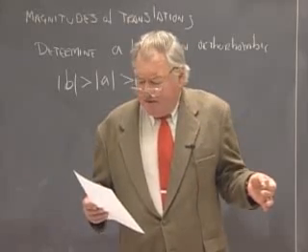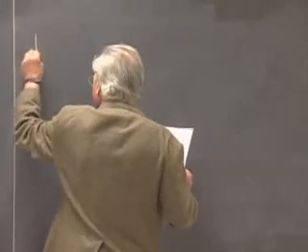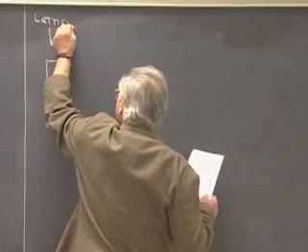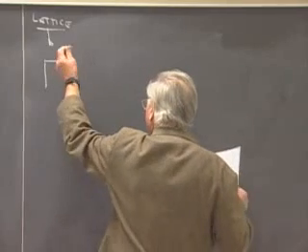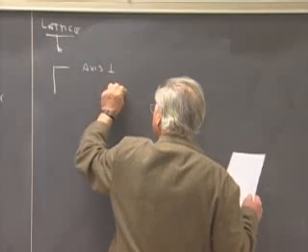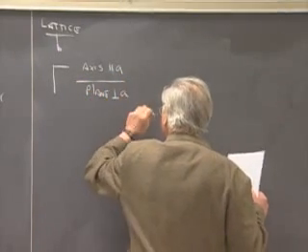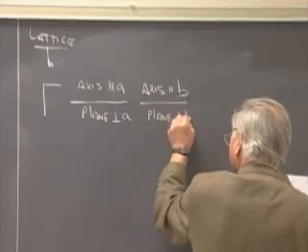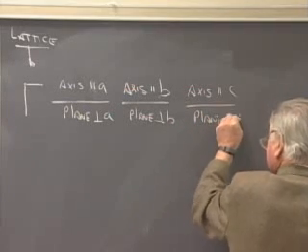All right, what symmetry goes first? And here, again, for orthorhombic, we need a convention. And the space group symbol has a symbol for the lattice type. And we've seen that the capital C that comes first indicates that there is a C-centered lattice. And then what one does for orthorhombic is give the symmetry elements in the order A, B, C. So the axis that is parallel to A over the plane that is perpendicular to A. Next, the axis that's parallel to B over the plane that is perpendicular to B. And then the axis that is parallel to C over the plane, if any, that is perpendicular to C.